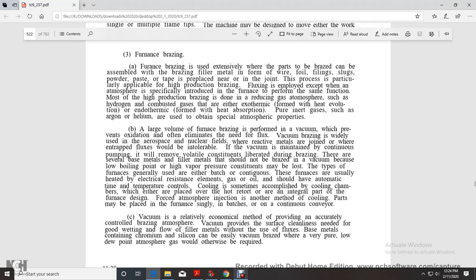A large volume of furnace brazing is performed in a vacuum to prevent oxidation and eliminate the need for flux. Vacuum brazing is widely used in the aerospace and nuclear fields, with reactive metals are joined, or where entrapped fluxes would be intolerable. They are maintained with continuous pumping to remove the volatile constituents liberated during brazing. There are some base metals and filler metals that should not be brazed in a vacuum because low boiling points and high vapor pressure can be a major problem.